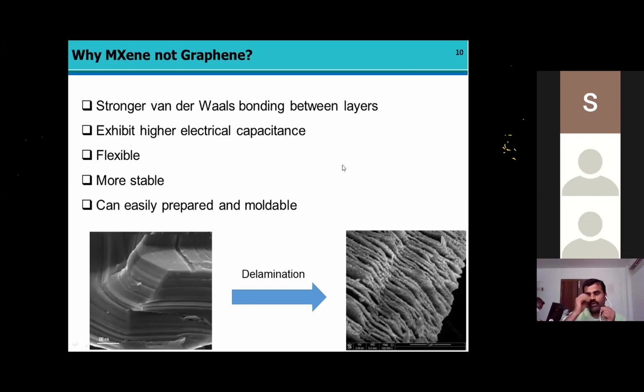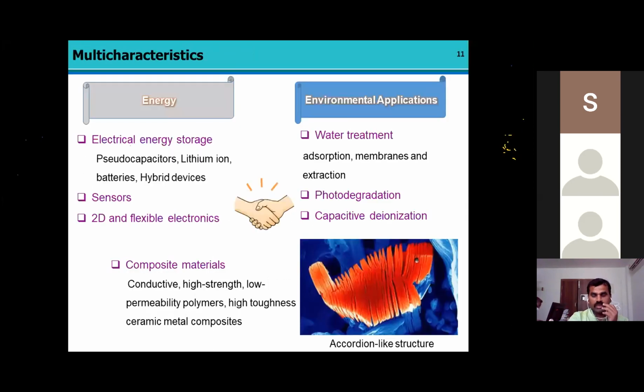Now, why MXene? Why not graphene? We know that graphene has a van der Waals interaction between the layers, but in the case of MXene, the interaction is much stronger than in graphene oxide materials. MXene exhibits higher electrical capacitance, is more flexible and more stable than graphene material, and can be easily prepared and molded into more forms than graphene oxides.